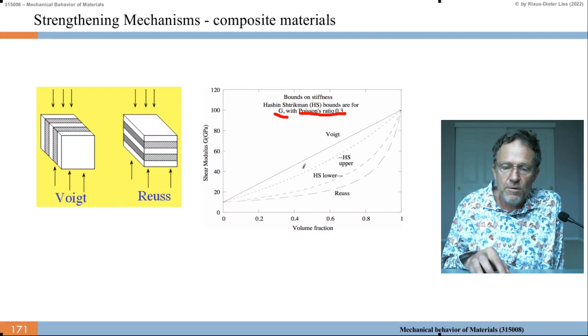And that gives you two boundaries closer to the Voigt situation. In the Voigt situation, you compress here and you widen laterally. But when you compress, you may also get shear stresses because you have different elastic moduli in the layers. So you get a higher and a lower boundary in this diagram by Hashin-Shtrikman, which lies between the Voigt and the Reuss. So the conservative model is without shear modulus and without Poisson's ratio, and if you do it more properly, you get this inner lens here.